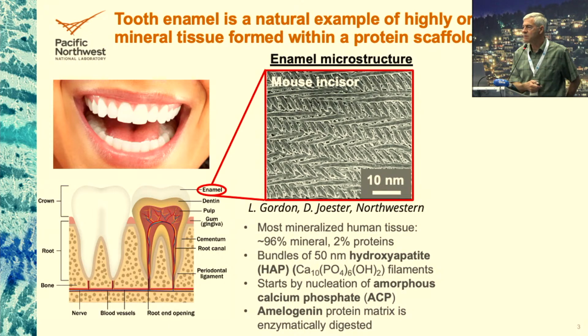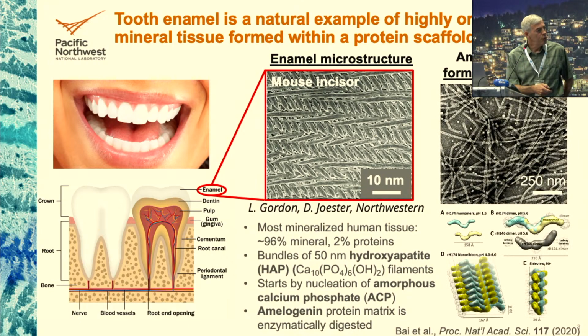So one of the big mysteries in biomineralization that many people have been trying to solve is, how does tooth form? Well, about a decade ago, a group at UC San Francisco, Stefan Habelitz's group, discovered that amelogenin, the protein scaffold that gets digested, has an amyloid region, and that if you bring it to a somewhat low pH, not too low, maybe 4 or 5, it self-assembles into a cross-beta sheet structure typical of amyloid fibrils. Of course, we think of amyloids as being part of disease, but amyloid is actually a functional structure as well. In this case, it forms two leaves. The hydrophobic sides are against one another, and the top and the bottom are identical.